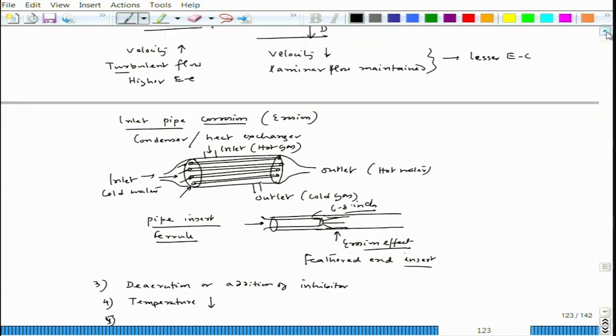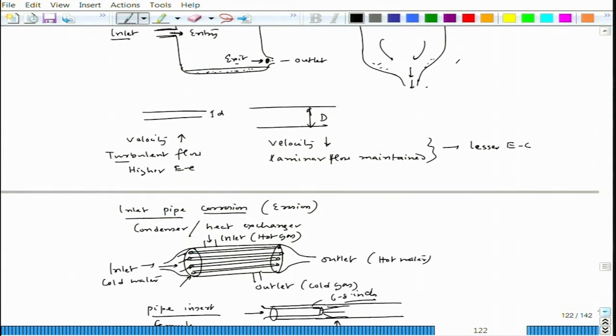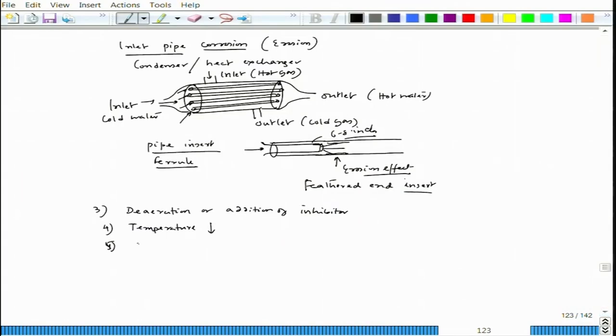Fifth is, of course, considering this particular design, clogging happens if we have a lot of dust particles in the water flow. If we have a filter plant before the water enters the main operation, that filtering process can reduce the erosion corrosion effect to a great extent because it filters out all those dust and dirt particles. So cleaning or filtering dust particles can reduce erosion corrosion. Temperature reduction also reduces erosion corrosion. Addition of inhibitor or deaeration can also help, but deaeration is not a very convenient process.